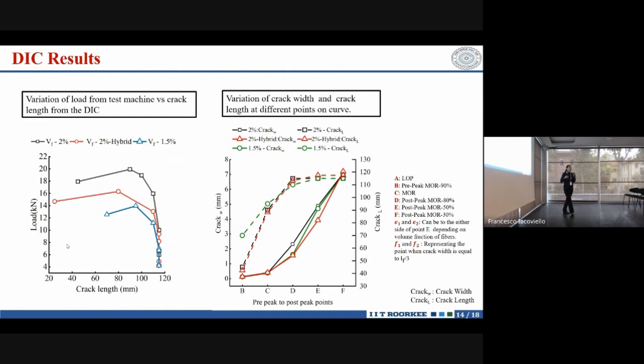It's like short fibers are working in the initial stage to bridge the micro cracks, but as the crack propagates, the larger fibers come into the picture. The small fiber length also helps to suppress the crack propagation, and that dense barrier that is made with the help of the short and long fibers will help to delay the crack propagation.